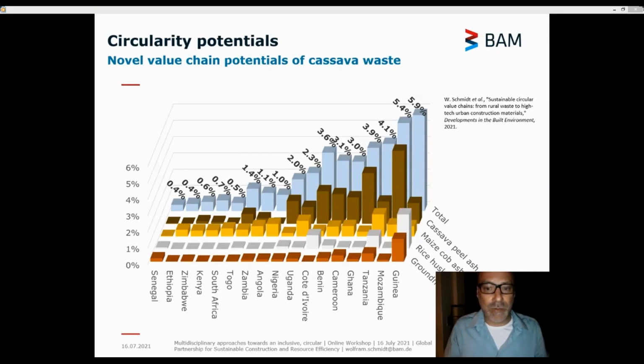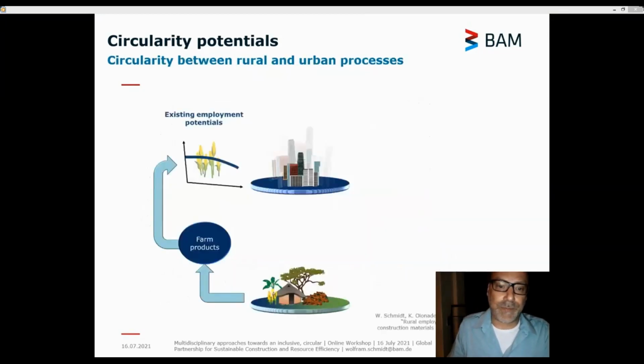So there's a tremendous growth potential, and 60% of the global arable land areas which are not yet used are on the African continent, which is another huge growth potential. And all of a sudden we talk about 15, 20, 25% of replacement possibilities, and then we are even higher than the ratios that can be replaced by fly ash or by ground granulated blast furnace slag, for example, which are established in the industrialized countries.